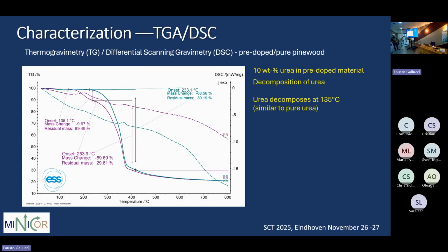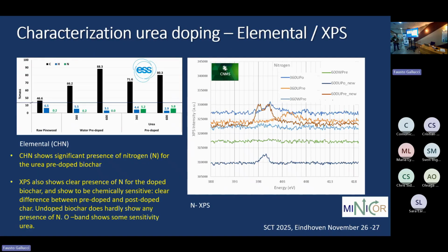This is a gravimetry example of pine wood pre-doped with urea. From that, you can see that our doping contains about 10% urea. That's the level of doping we have. And from the DSC, the differential scanning calorimetry, you see that the urea breaks down and gives a signature.